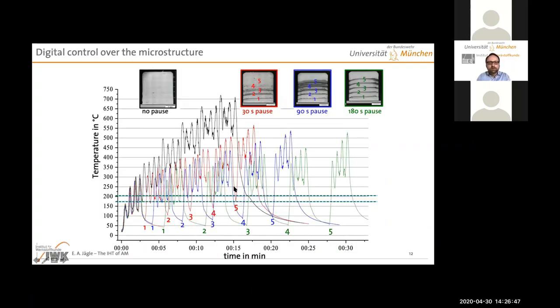All right, now that we've understood this, we can start to play, of course. We can vary the pause time. We can go to 0 pause, and this temperature again is at the very bottom, right next to the very first layer. Sorry, this is a very busy graph, but I hope you can get what I mean. The black curve is no pause time. And you see in the etched specimen, nothing is dark. So no hardness. Why? Because we're never going down below the martensite start temperature. Everything is always austenite. And the temperature goes all the way up to 600 degrees. And only then the process is done and we cool down.